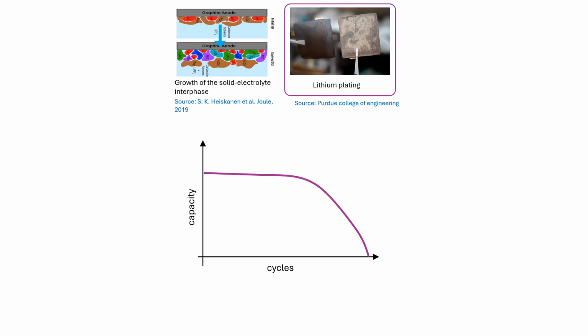Lithium plating is another first principle battery cycle life predicting method. This is an example of a battery capacity fading curve. The curve can be divided into 2 regions. The first one is called linear region, where the capacity degrades slowly. The degradation in the region is mainly contributed by the SEI formation we just introduced. The second region, where the battery capacity degradation really starts to accelerate, is mainly contributed by lithium plating.